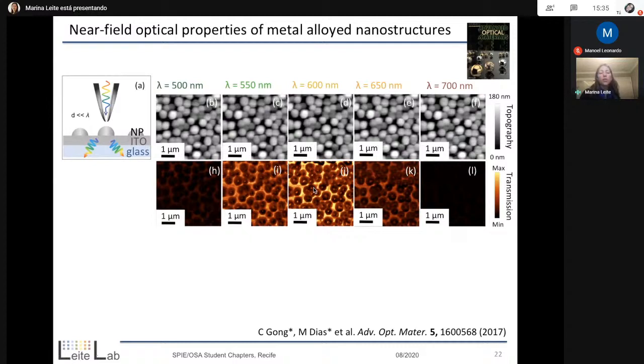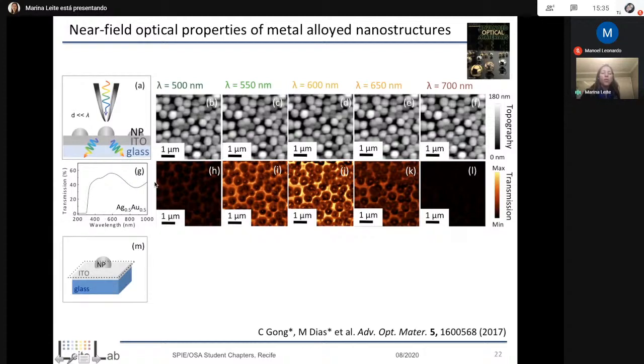So then we essentially combine these experiments with simulations, 3D full-field simulations. This is just a graph showing how the nanoscale behavior is in very good agreement with the macroscopic transmission measurements, that's all. But anyway, so what we do is that we simulate this 3D scenario. We simulate our metallic nanoparticle, the indium tin oxide, the ITO transparent material here, and our glass substrate.